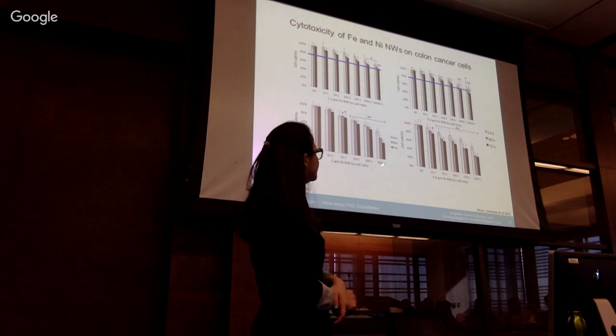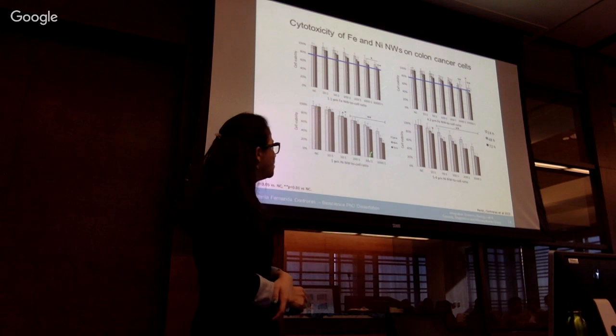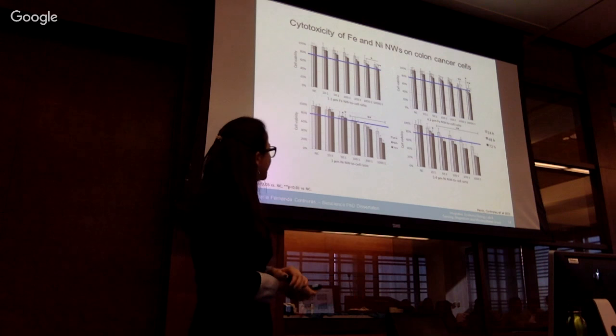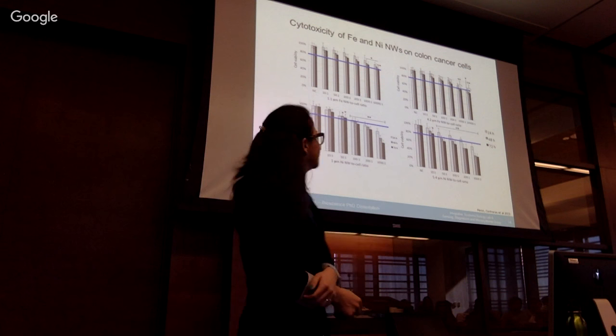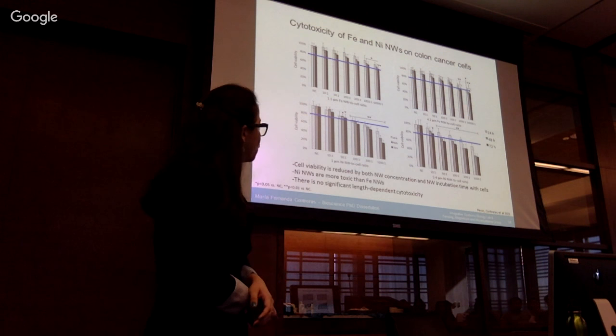The only difference is that here we only tried up to 1,000 nanowires per cell. We didn't go higher, because viability was already decreased a lot. And again, taking this reference, here we have that this threshold is surpassed for lower concentrations at earlier time points. So from this set of experiments, we can first see that